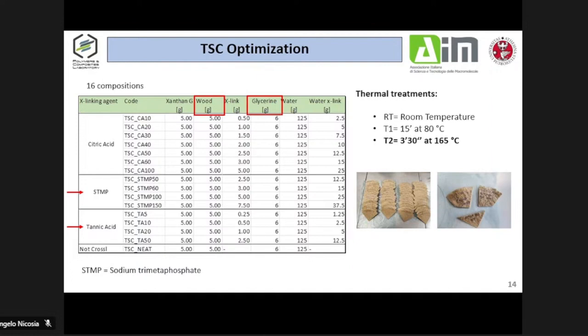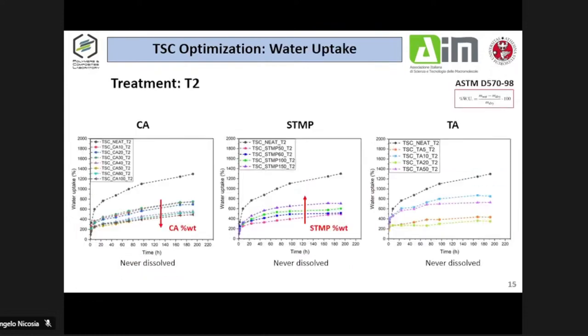We tested the material at three different conditions of temperature, and we put the materials in water to evaluate the water uptake and the swelling degree. And we found that in the first two cases, at low temperature, the material dissolved after a few days, but at T2, so 165 degrees C, the material resists in water. In particular, we performed the test cyclically, multiple times, and for citric acid, we have the best response, with material which never dissolved in water. So we have a good water regulation of the material.